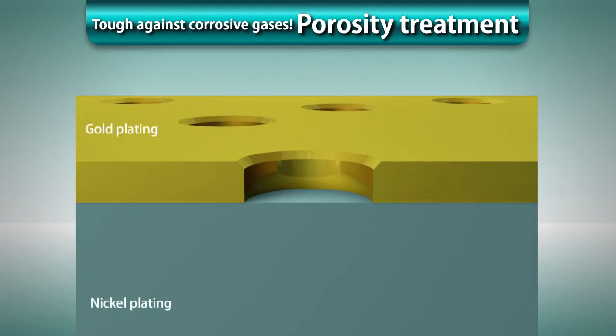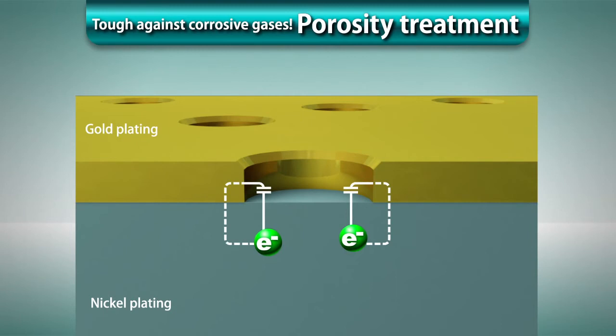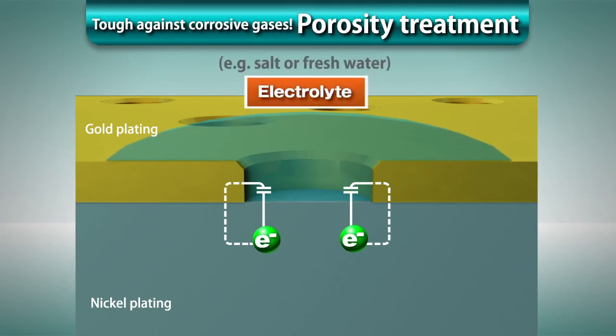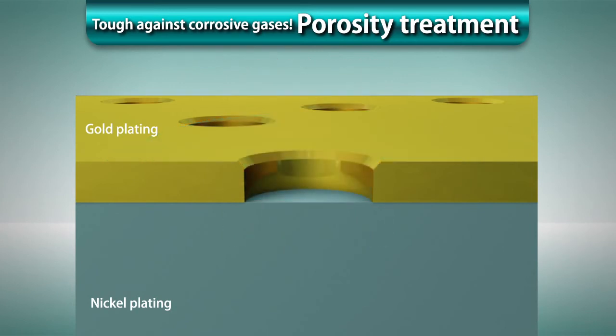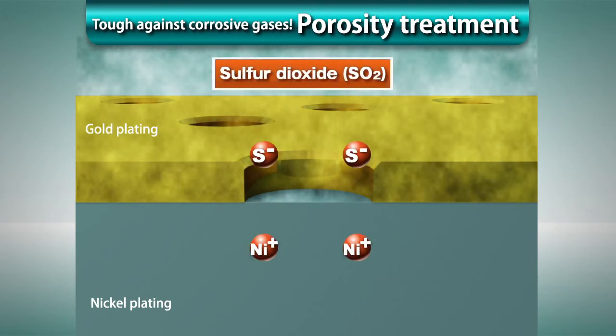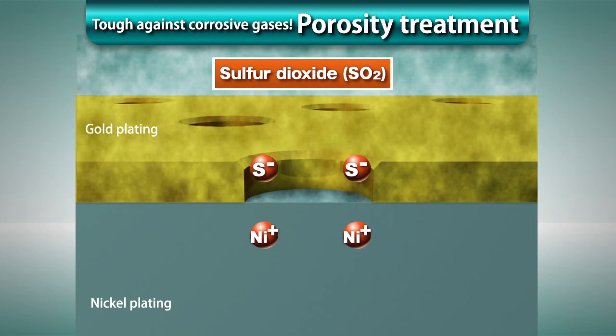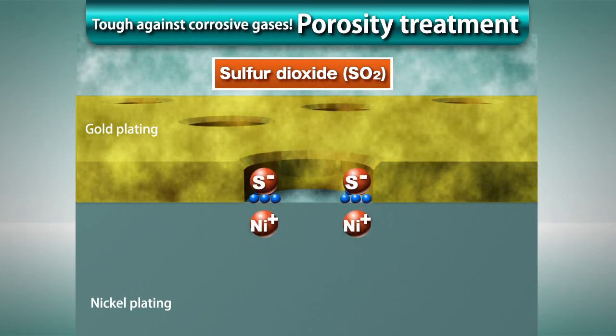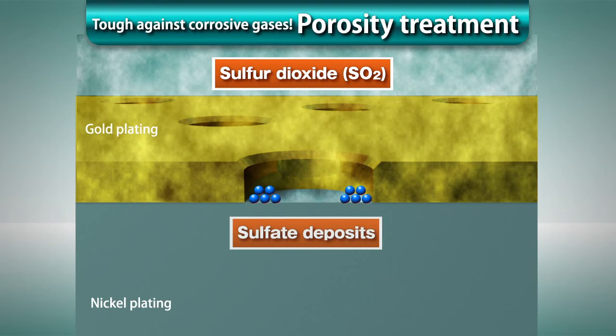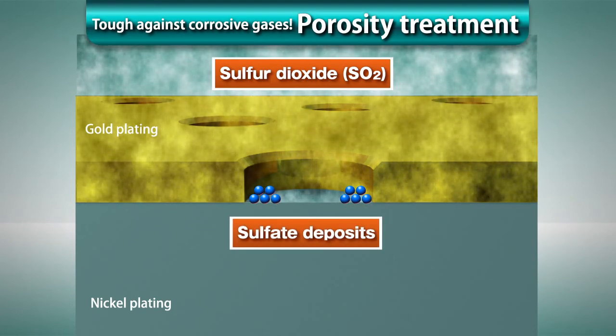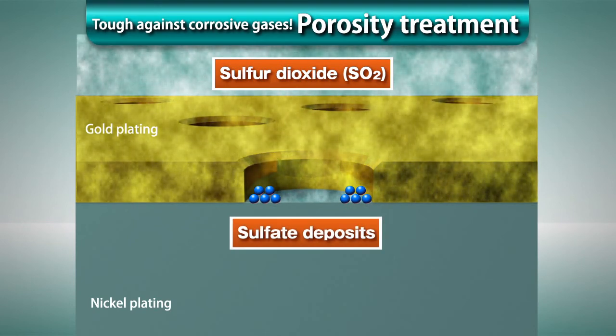At the interface between the gold-plated and nickel-plated layers, a local cell is formed due to the potential difference. This local cell action is further accelerated by the presence of any electrolyte, such as salt or fresh water. When sulfur dioxide increases while the local cell action causes the nickel-plated layer to become susceptible to sulfurization, they are combined, depositing an insulating material and thereby causing corrosion.